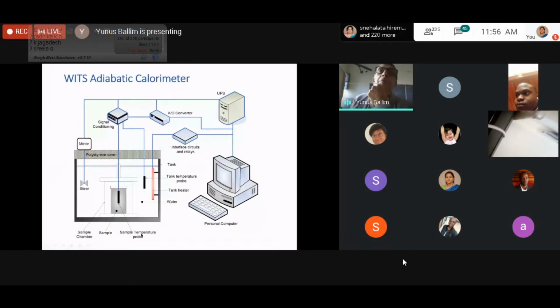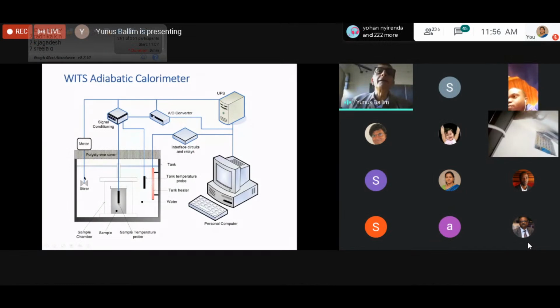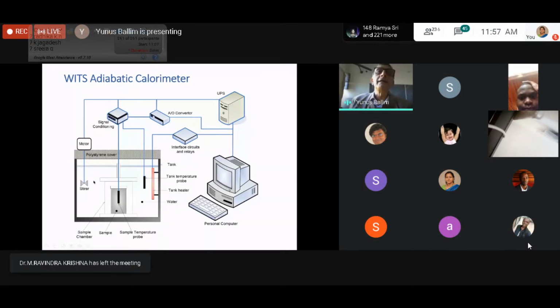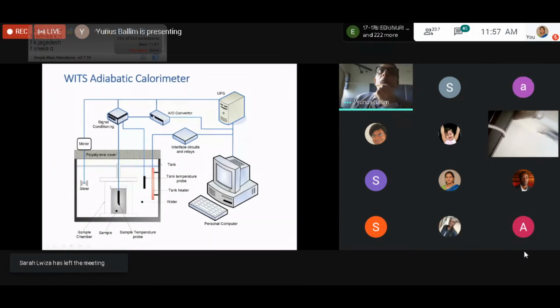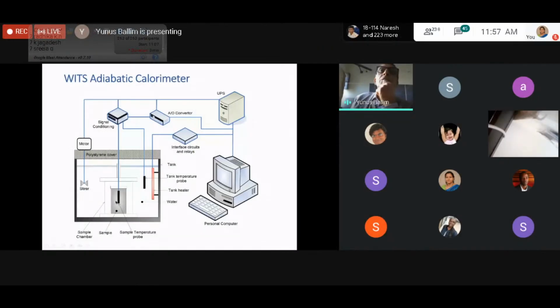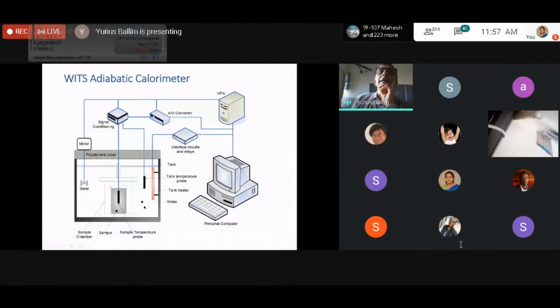We developed this, it's really a completely homemade calorimeter. It works very well. So what we have is we have a sample of concrete. This is real concrete, so it's a stone, it's aggregate with water and cement. That's about 1 liter of concrete there. We have a temperature probe in the concrete, and that is sitting inside of a bath of water, which has a heater element and a stirrer. The motor is outside of the water so that it doesn't add heat to the water. The computer system monitors the temperature of the concrete sample, switches on the heater or off to make sure that the water is exactly at the same temperature as concrete. And if you can manage to maintain these two temperatures the same, then you've got adiabatic conditions. In other words, there is no heat exchange between the sample and its environment.